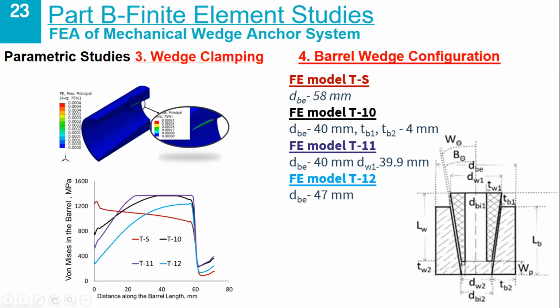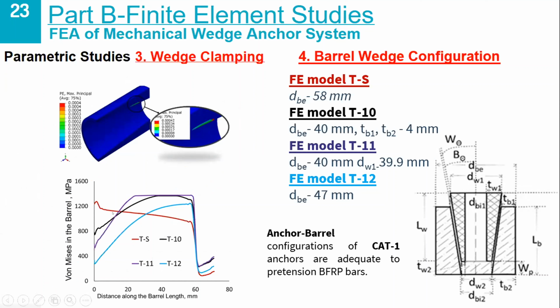So 4 different models have been investigated with different thickness of the barrels as well as the wedges. And these are the different plots for the von Mises stresses that have developed in the wedges with the distance along the barrel length. And you can see that the standard category 1 anchor that has been used did not undergo any yielding phenomenon, and the stresses in the other configurations that were investigated were higher. So hence it was concluded that the configuration of the category 1 anchors are adequate for the pretensioning of the BFRP bars. Any change in the barrel and wedge thicknesses would result in higher stresses, which would cause the yielding of these anchors and the barrels.